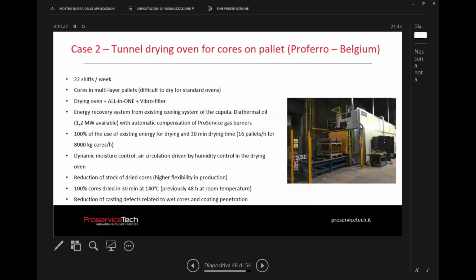This is Proferro in Belgium. This is a multi-purpose drying oven. In this case, for all this roof here, we use the energy coming from the cupola, the diathermic oil, to dry the cores. The only moment in which we use the gas burners is when they don't have enough diathermic oil, but otherwise it's completely cheap, zero consumption of natural gas. And you can easily put what you want, big cores, even a steel pallet on top of this. It is very flexible.